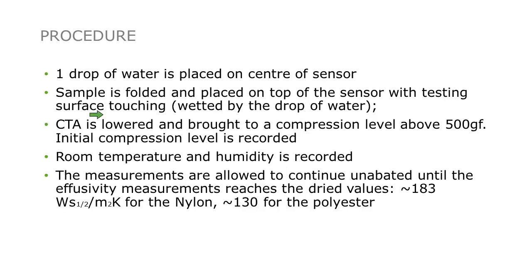I'll just explain a little bit the test procedure that was employed in this testing. So 1 drop of water was placed in the center of the sensor. The sample was folded and placed on top of the sensor with testing surface touching.